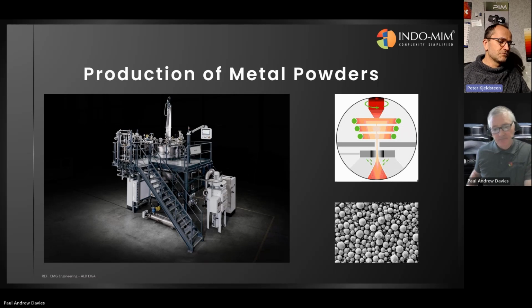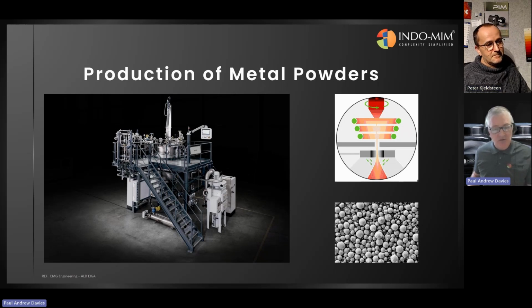I remember when I was working with atomization, we were working with some alloys that had a high tendency of clogging in the ceramic nozzle. So instead of going to a very high superheat, we looked into the possibility of adding an induction coil around the tip of the nozzle to avoid it from clogging. Yeah, absolutely. Depending on the alloy and its constituents, clogging can be a problem. For instance, if you're using nitrogen gas, you can create nitrides, or if it's a sensitive alloy from an oxides point of view, then you can get a buildup of oxides in the nozzle.